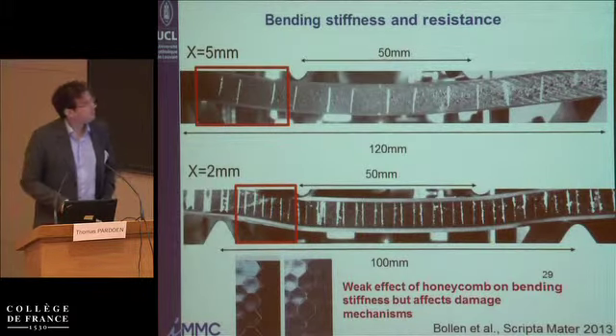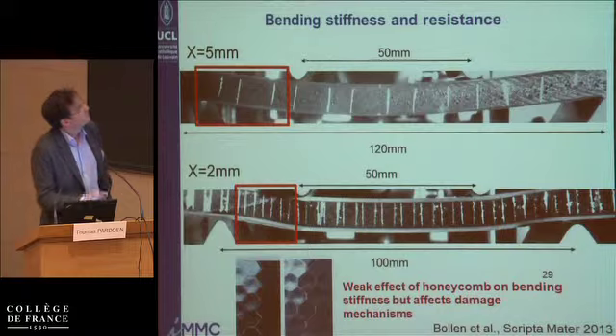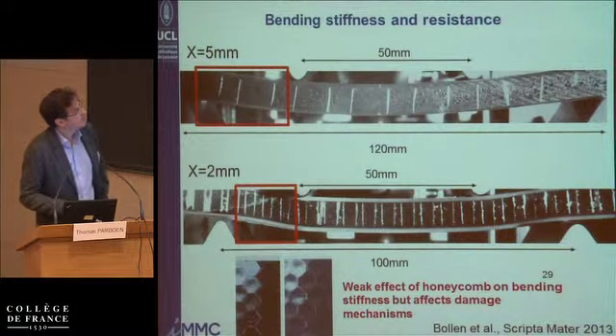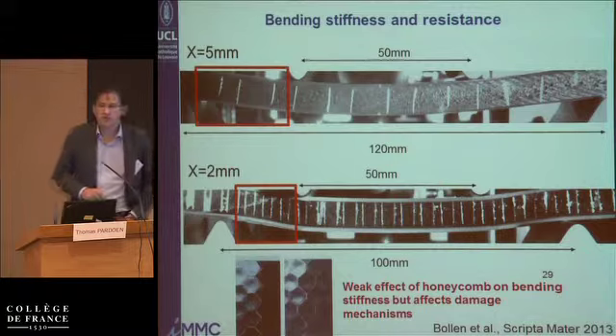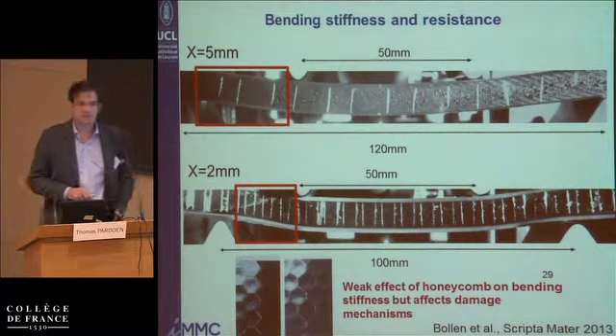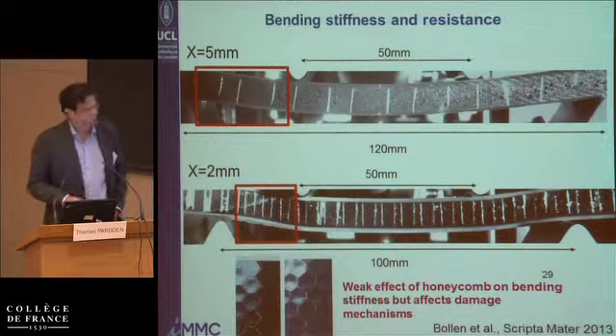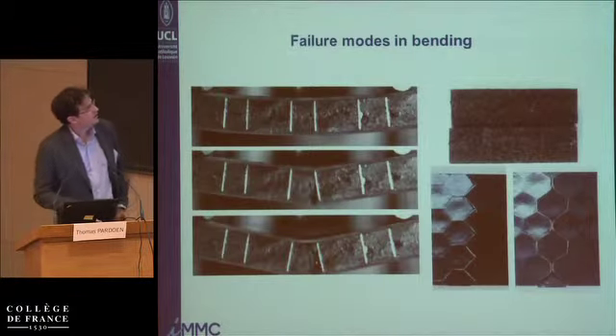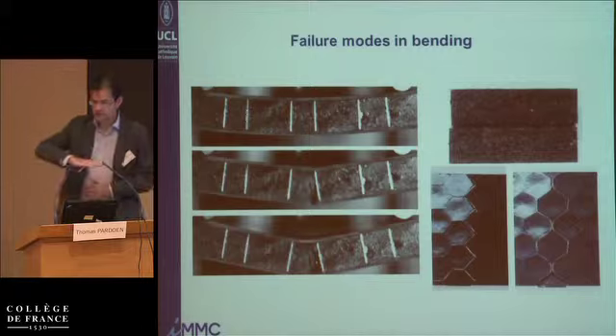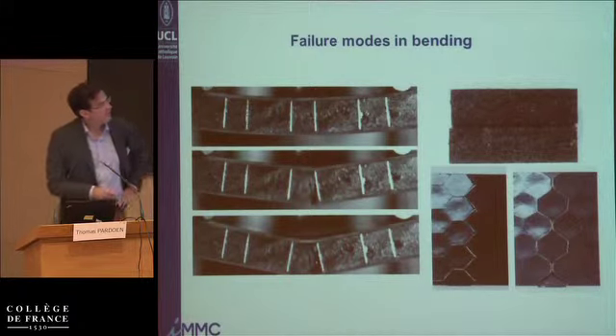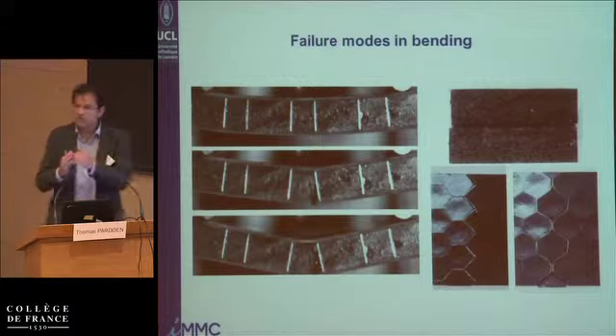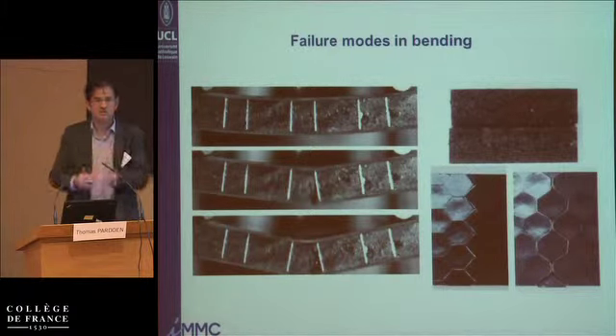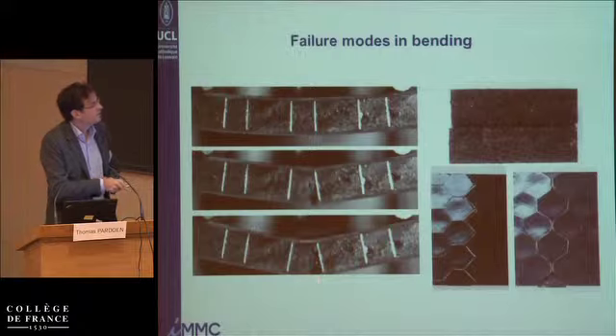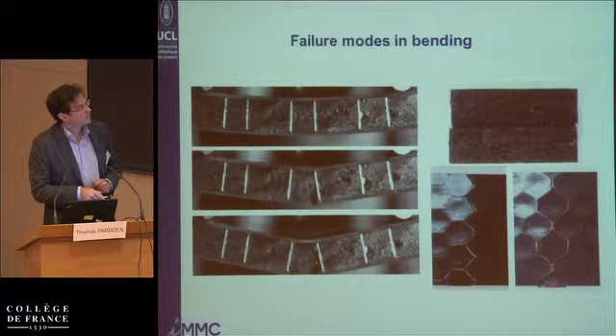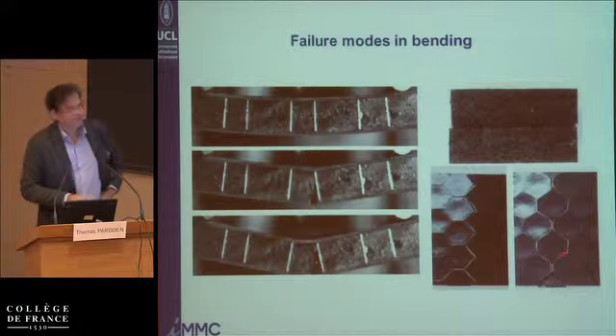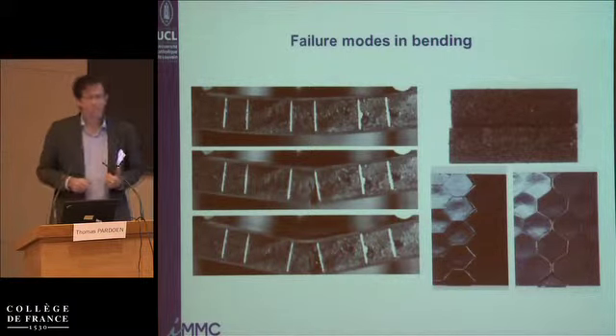We have performed bending tests on different sizes of honeycombs and different thicknesses in order to evaluate the bending modulus, as well as to detect the failure modes. And the failure modes are indicated here. Depending on the orientation of the honeycomb with respect to the bending, we're getting either decohesion between the foam and the face of the honeycomb, and then finally decohesion of the face sheet, or sometimes decohesion between the layers of the honeycomb.